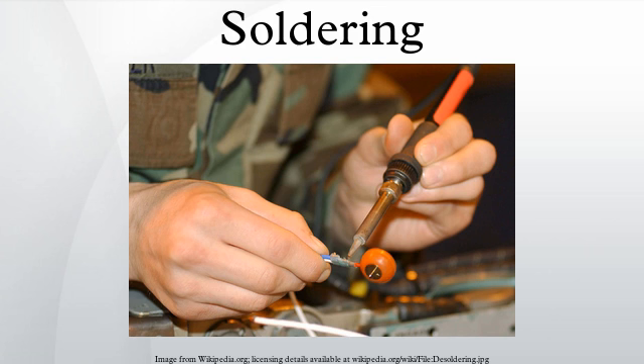It is highly recommended to use a device that can remove the fumes from the work area either by ventilating outside or filtering the air. It is a common misconception that lead-free soldering requires higher soldering temperatures than lead tin solder. The wetting temperature in lead-free solder is higher than the melting point and is the controlling factor. Wave soldering can proceed at the same temperature as previous lead tin soldering. Nevertheless, many new technical challenges have arisen with this endeavor. To reduce the melting point of tin-based solder alloys, various new alloys have had to be researched, with additives of copper, silver, and bismuth as typical minor additives to reduce melting point and control other properties.